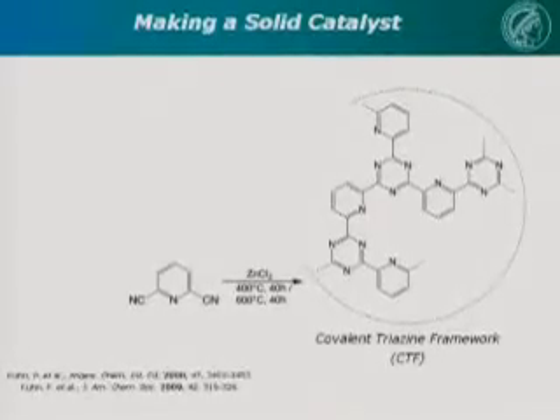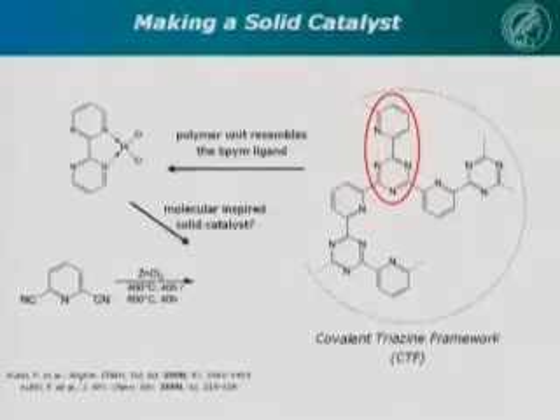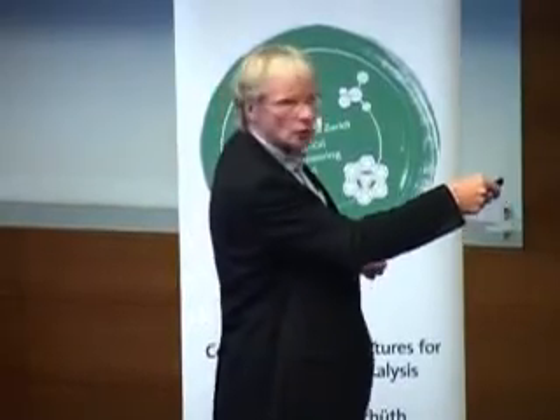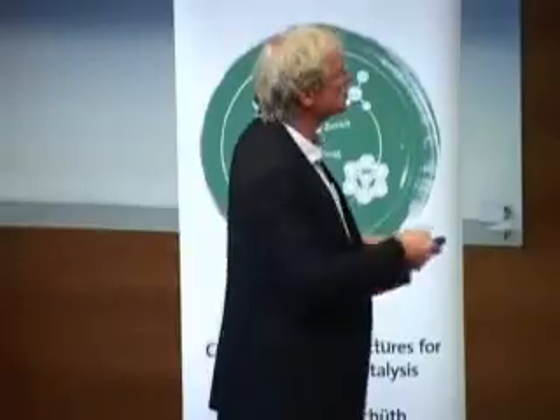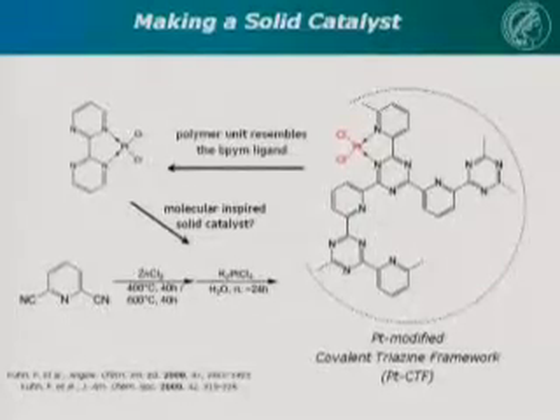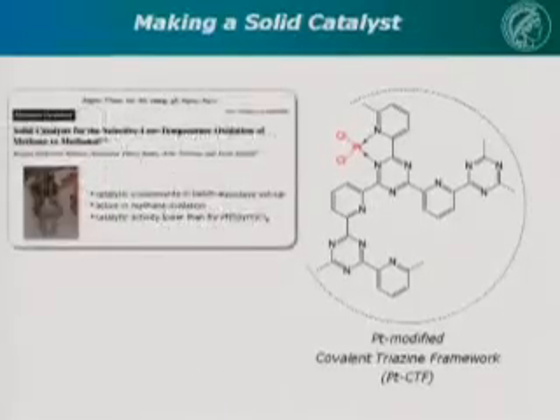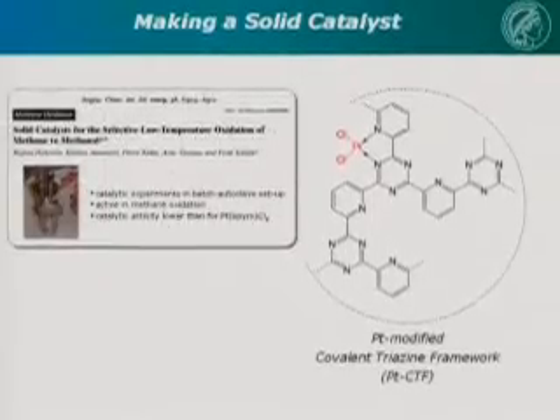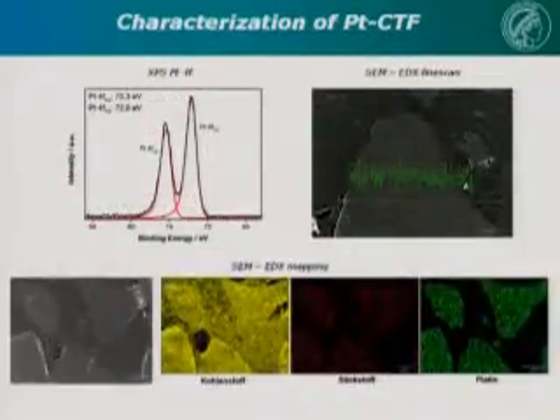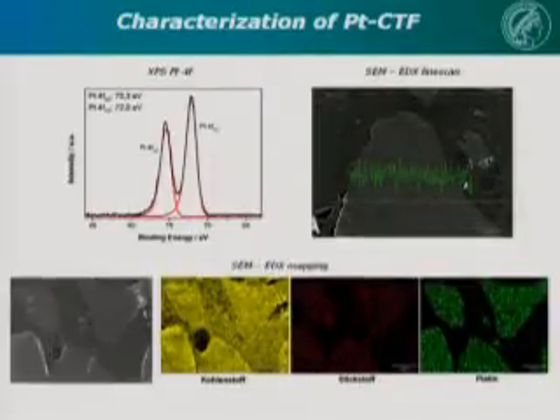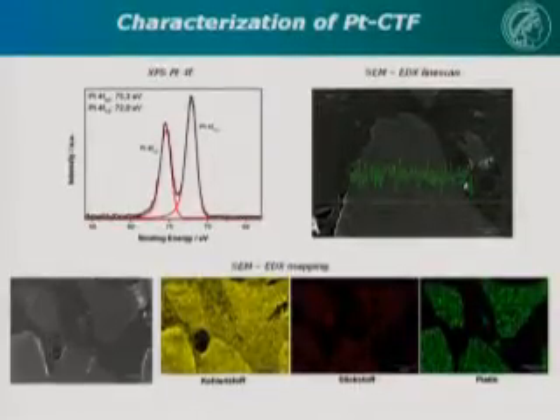And this was one of the very simple ideas which basically should not work, but in this case it did. I at that time told the student working on this, why don't you just throw platinum on the solid and see whether the platinum doesn't coordinate like in the Periana catalyst to the solid. So we just added potassium tetrachloroplatinate, and indeed we got a catalyst which basically did the same as the molecular Periana catalyst. At that time, we couldn't do proper experiments. I'll tell you in a second why we couldn't do proper kinetic experiments, which we now have. But first, briefly, the analysis of the catalyst.